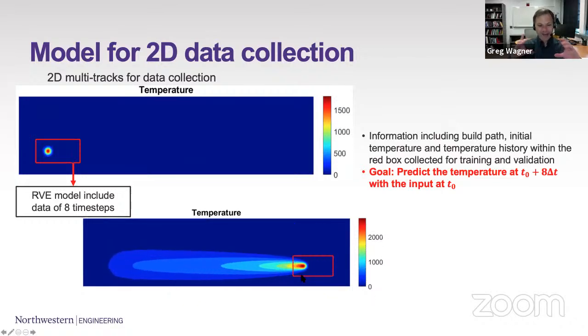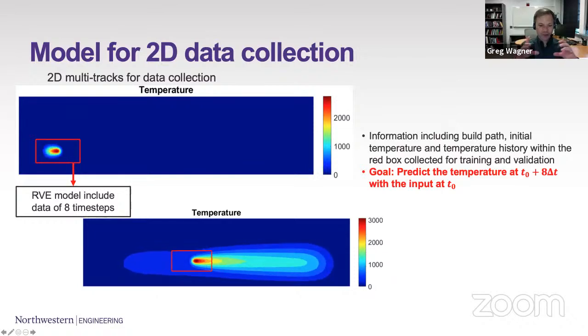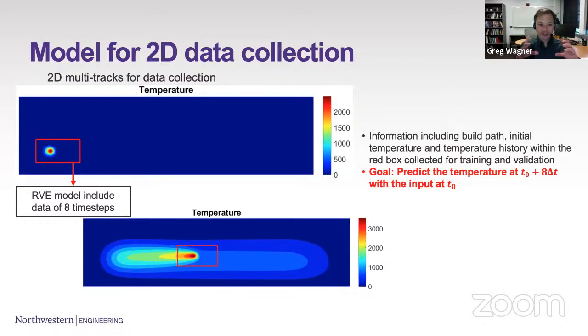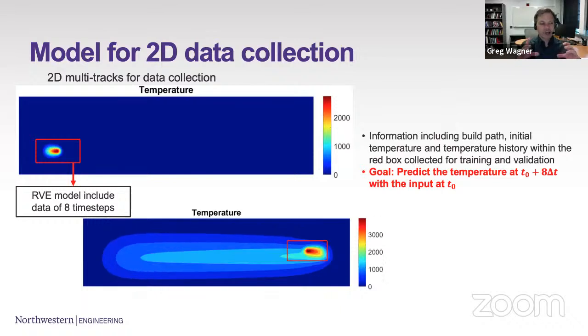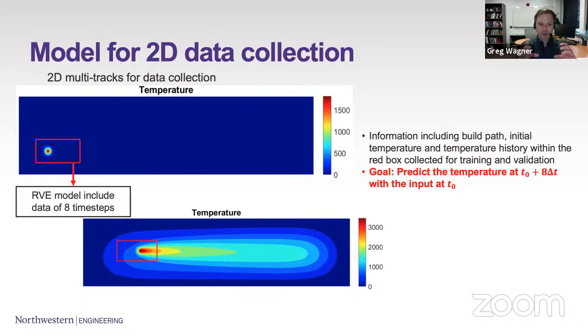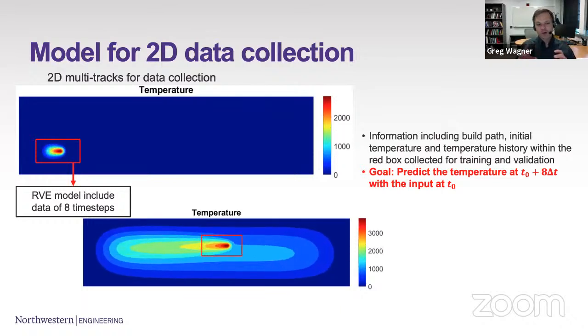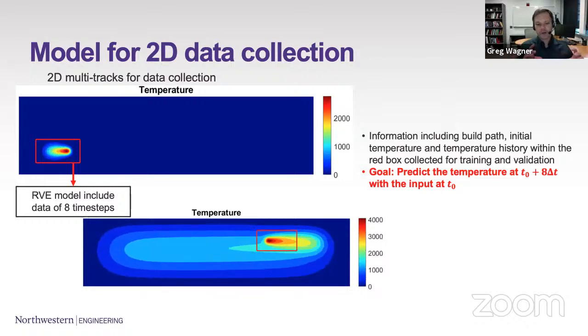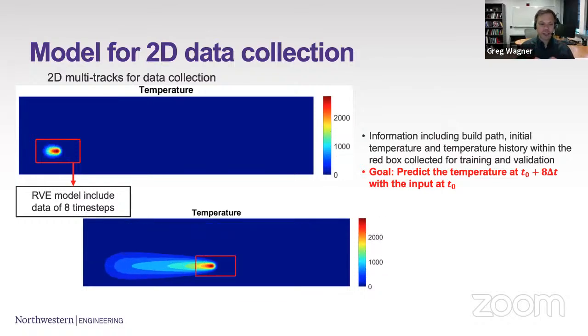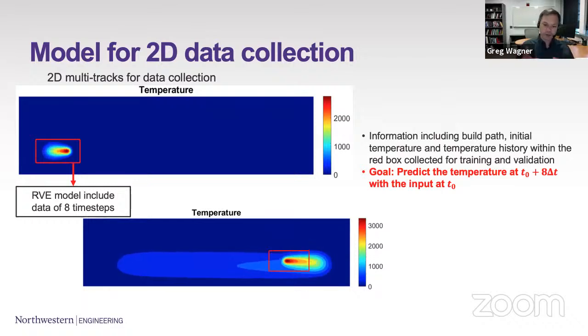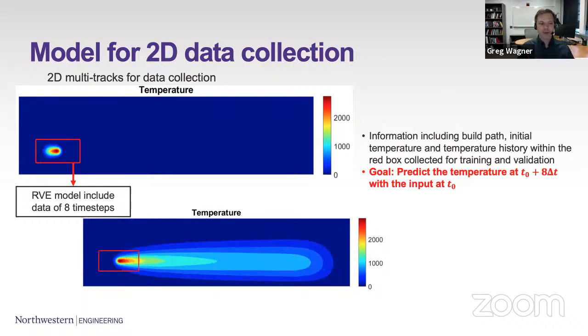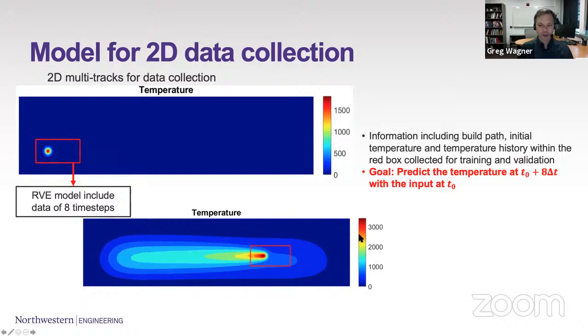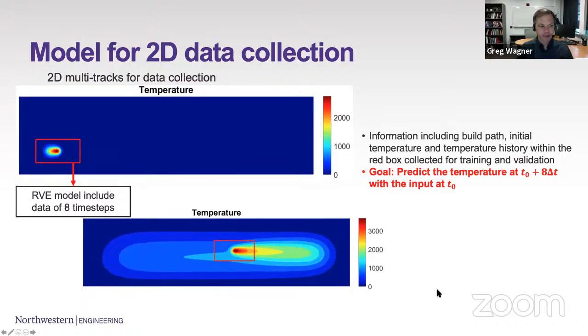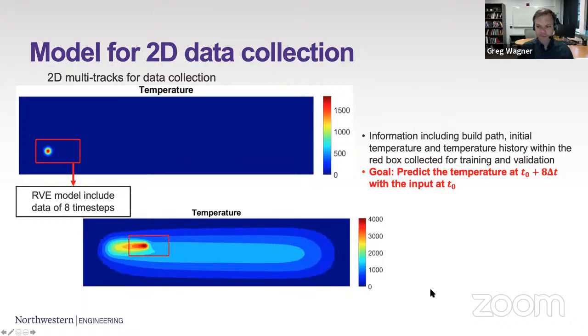This red box is showing our representative volume region, where over this region we're sampling data over a given amount of time. That includes both regions where the laser spot is moving in a straight line and where it's turning. We can vary the process parameters, the scan speed, the hatch spacing and things like that, in order to gather as much data as possible from these simulations.